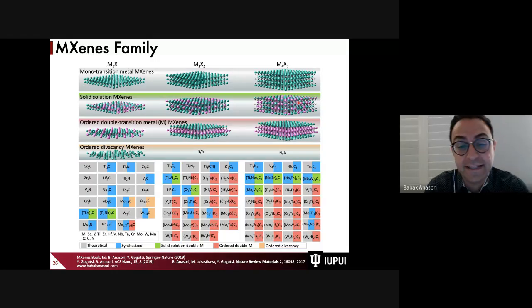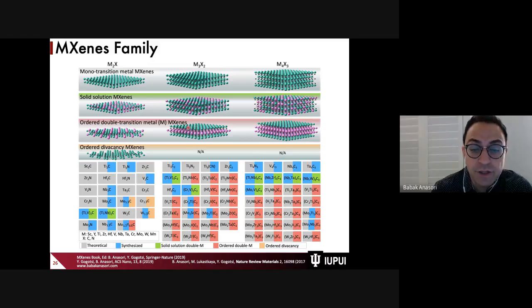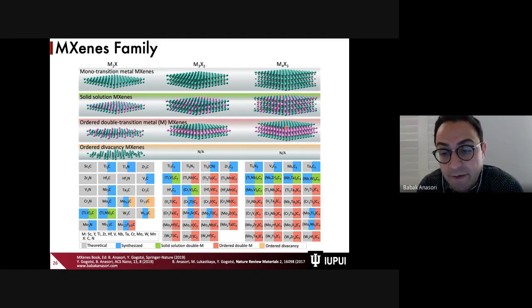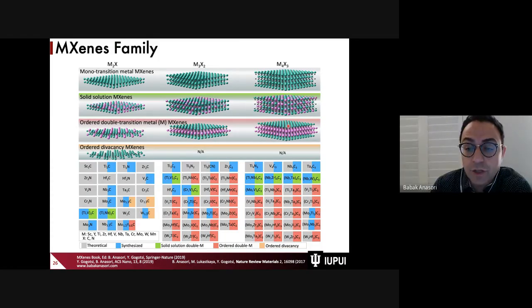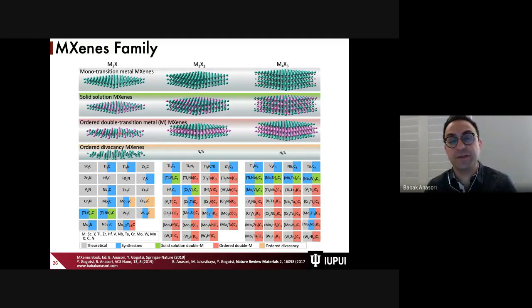Another unique feature of MXene is that when we mix certain transition metals, instead of forming a solid solution, they form ordered structures, meaning that one element, for example molybdenum, will go in the outer layers and titanium will go in the middle. So they form these atomic sandwiches at the 2D level of the carbide. So here we have only 4 layers of atoms with carbon in the interstitial sites, and we have these atomic sandwiches of molybdenum and titanium. We can even go one step further, and we have in-plane ordering, which means that we are looking at one plane of atoms where we have ordering of different elements.